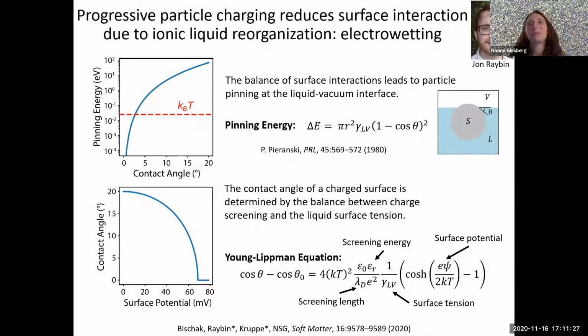And so here John parameterized it in terms of the contact angle the liquid makes between the particle surface and the interface it makes with the vacuum or the vapor. Right? So when there's a charge on the particle and the ionic liquid reorganizes near its surface in order to screen the charged particle's field, we already inferred that the contact angle should change. This is really equivalent to saying that the particle goes deeper into the liquid because more of its field can be screened. The dependency of the change in contact angle as charge is added to the particle can be encapsulated in this Young-Lippmann equation and is the principle behind what we would typically call electrowetting.